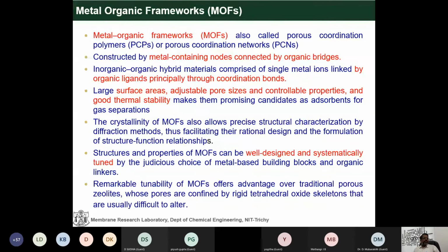Most of you know what a MOF, a metal organic framework, is. Metal organic frameworks are porous coordination polymers with porous coordination networks. They are constructed with metal-containing nodes connected by organic bridges, linked with organic ligands principally through coordination bonds. So what is the advantage? You have these organic-inorganic bonds. I told you that nanomaterials by themselves aggregate due to the inorganic phase. But here the linker bonding is organic with an inorganic bridge, which is more responsible for uniform distribution of the inorganic material in the polymer, avoiding agglomeration and aggregation